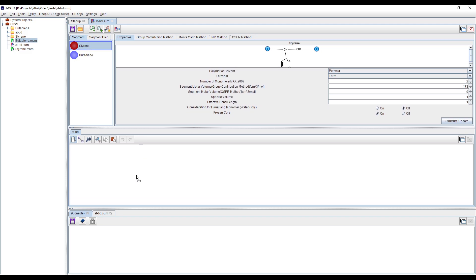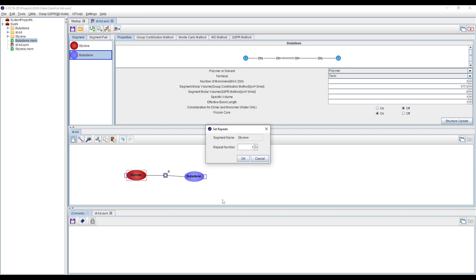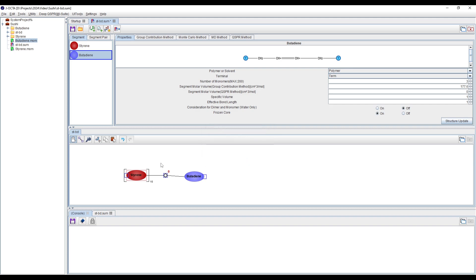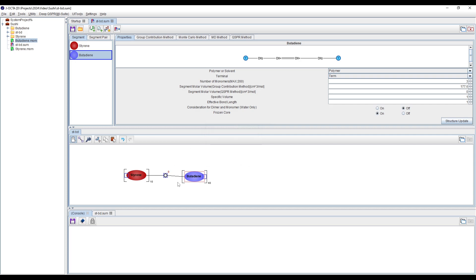We are going to drag and drop styrene and butadiene into the working area. To create an interfacial structure, we need a junction point — select the junction point, then use bond formation to make the bond between styrene and butadiene via the junction. We also need to increase the number of repeat units to make it a polymer: 10 monomers for styrene and 40 monomers for butadiene. We are done with the creation of our polymer system separated by the junction.